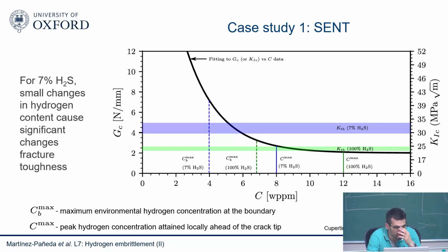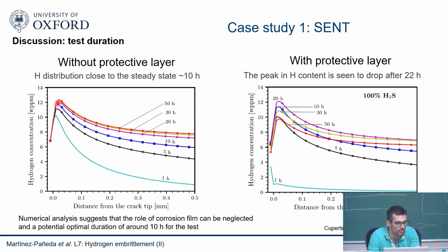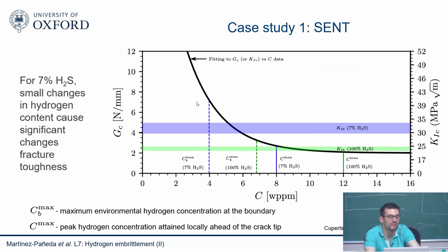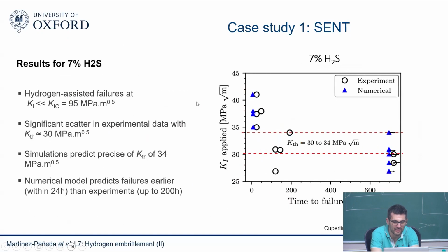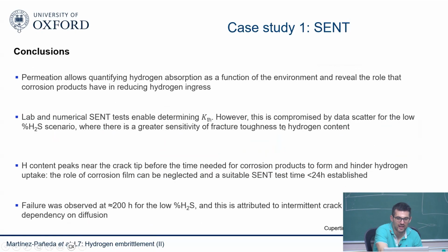But in the case of 7% H2S, it is the opposite effect. We see a big drop. We are in a regime where the slope is very high. So a tiny change in hydrogen concentration, due to the fact that we waited a few hours more, or because the corrosion barrier protected my surface a bit more or a bit less, is going to have a big change in toughness, and therefore that is what brings the scatter that we see in these experiments. So this is what we are basically highlighting with the model.